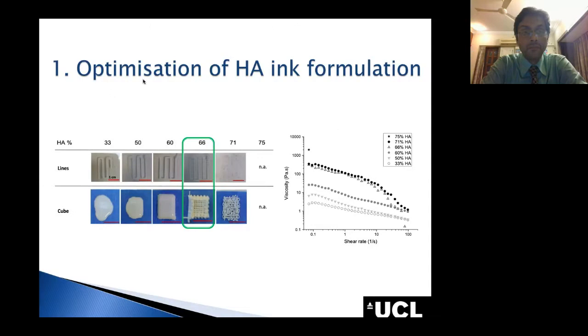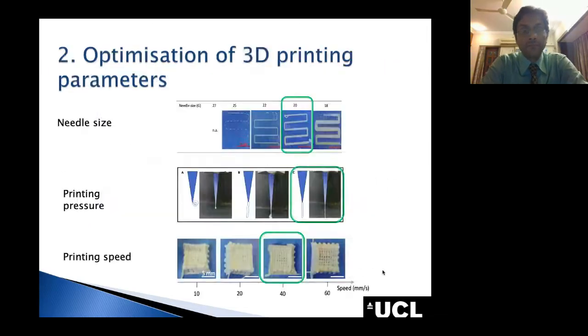We saw that by increasing the hydroxyapatite concentration in the binder, which was based on hydroxypropylmethylcellulose, the printing quality and the printability increase up to a point before it is not printable anymore, and so does the viscosity.